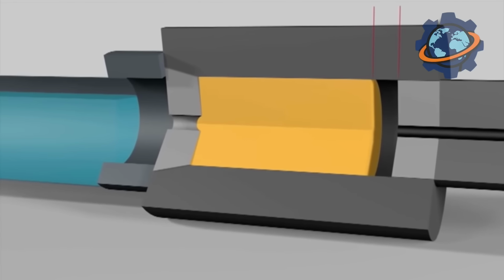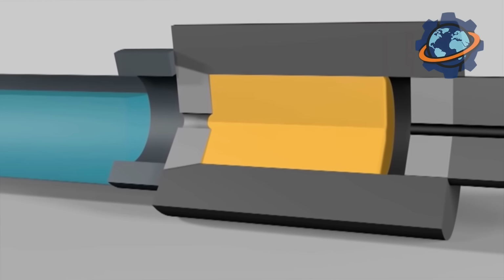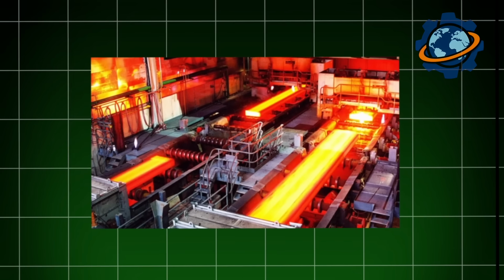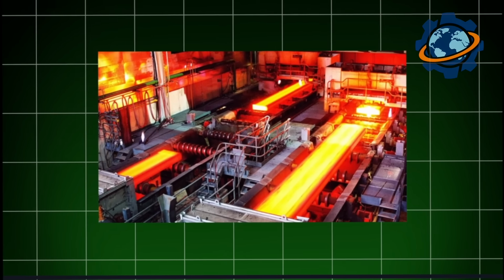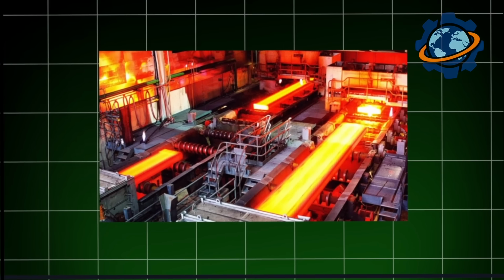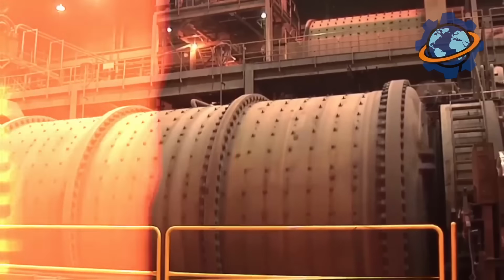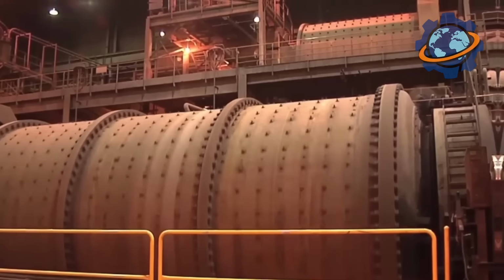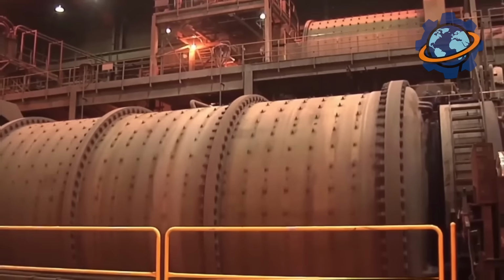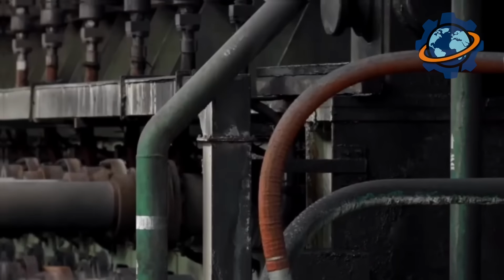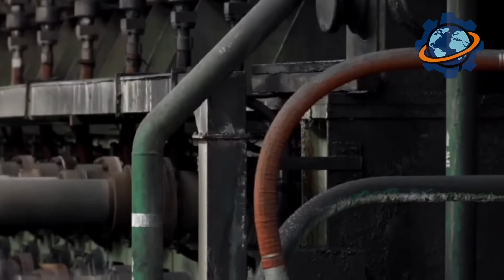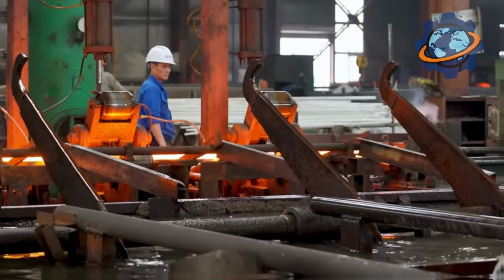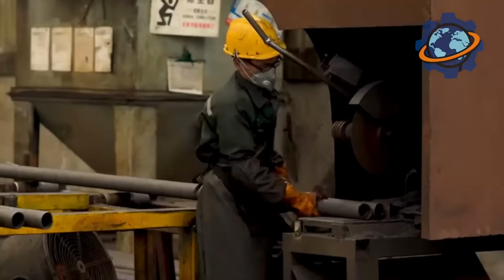It passes through the next pair of rolls, even thinner, dozens of times. An 8-inch thick slab becomes a sheet 1 to 2 millimeters thick. Length grows from 33 feet to over half a mile. Rolling speed on finishing mills reaches 50 miles per hour. Red-hot steel ribbon flies through the mill, sparks flying everywhere.